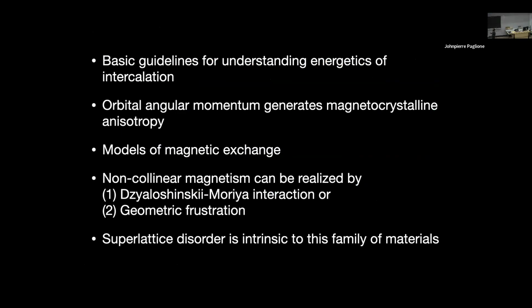So what I hope to accomplish today is to provide a basic guideline for understanding the energetics of this intercalation from a chemical perspective, just a couple of slides on that. What can intercalate into what? How should we think of these? Why is it that niobium and tantalum are the dominant host lattices for this, and not, say, molybdenum disulfide or tungsten disulfide, which might be interesting if that could work? Then we'll go into the effects of single-ion anisotropy, the local ligand field around the intercalated ion, and how that affects magnetocrystalline anisotropy, looking at a couple of cases.